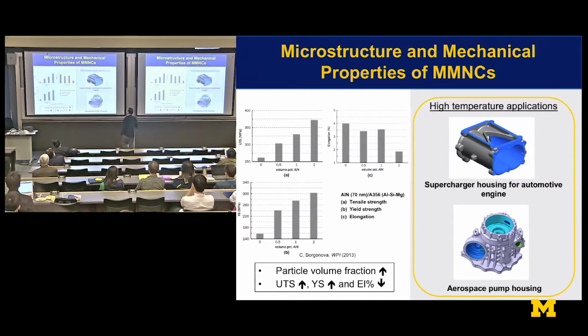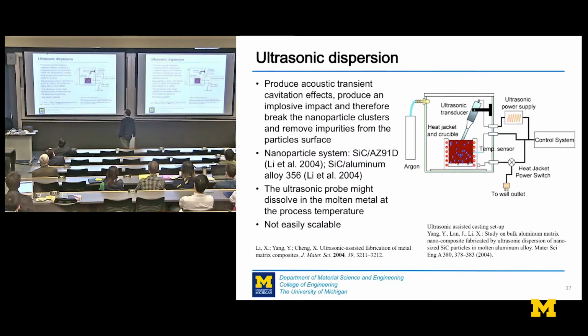There are lots of intermediate temperature applications where we would like to replace the castings with aluminum or go to thinner wall, and this can enable it. The problem is, and it's actually the inverse problem of what Sharon Glotzer talked about yesterday, our problem is not how do the particles collect. Our problem is dispersing them because they don't want to separate. The traditional way of doing that, by inserting the particles in the melt and ultrasonically dispersing them, really has not proved to be very effective when we get down to 50 nanometer particles.